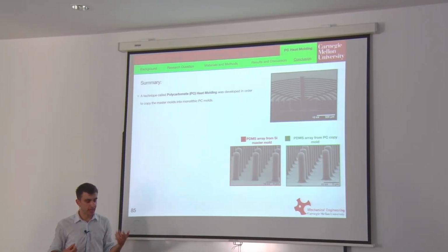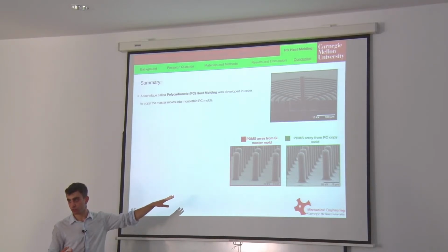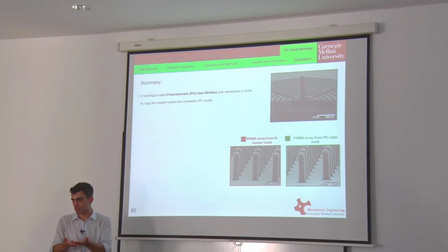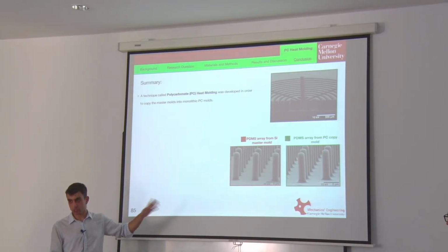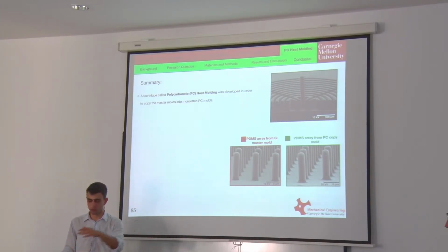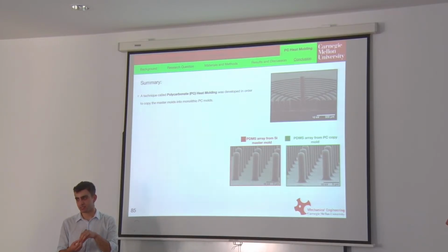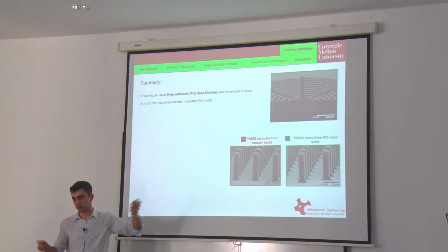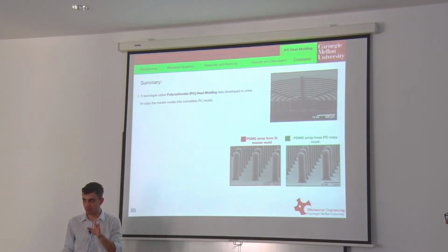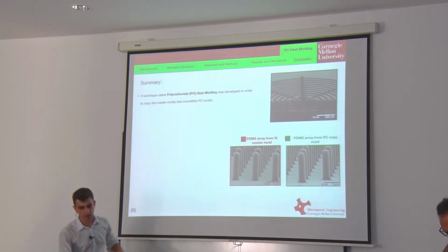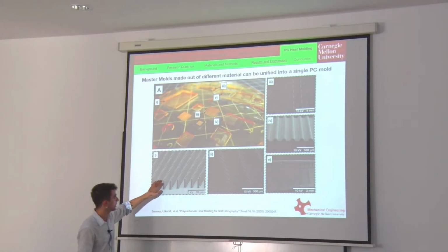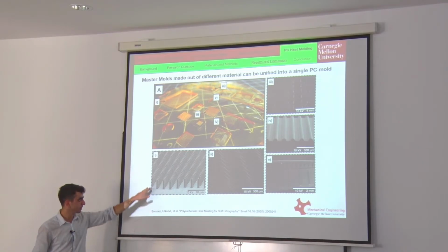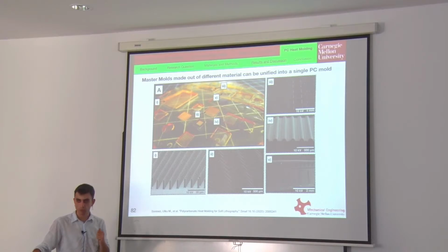One of our collaborators asked me to use this technique to make copies of the original mold, and if one of the molds that you multiply has this rupture issue, you can use the other one. But to minimize the rupture issue, which is very critical, we use a silanizing agent. We coat the wafers with a silanizing agent, which decreases the stickiness of the surface, so the PDMS parts can easily be removed without much problem. It can still happen from time to time, but it's not super hard. I got them for a really high surface area, with thousands of them in a very small area. They are really small, but it works fine if you use a silanizing agent to reduce the surface stickiness.